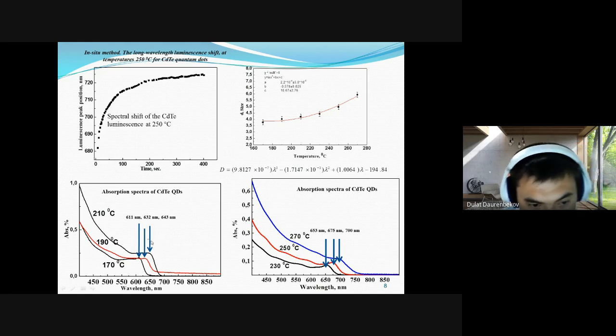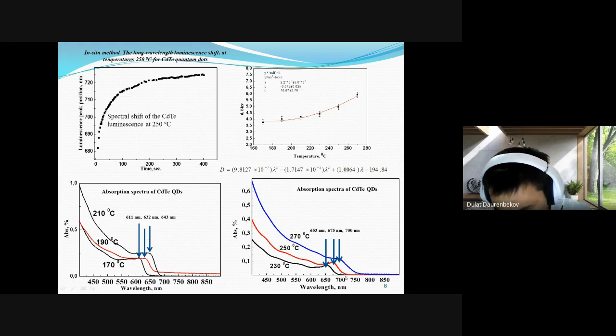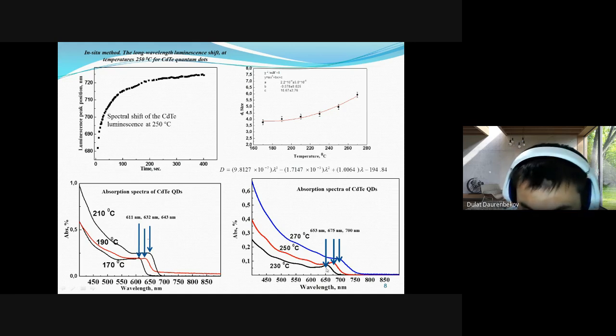And here are the absorption spectra of the final obtained quantum dots at different temperatures. As you can see, their band gap moves to the red spectrum, from 170, to 190, and to 210. It's almost 700 nanometers. And here is the empirical equation, where we can put the lambda in nanometers and calculate the diameter. And here is this calculation.